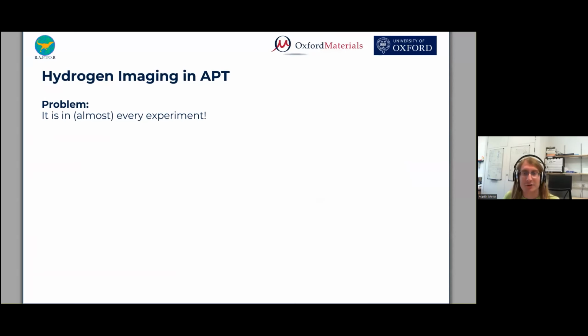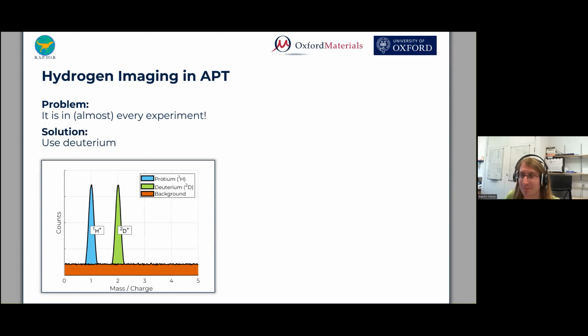We briefly return to the introduction. I said imaging of hydrogen is difficult because we never can be sure if the hydrogen is coming out of the sample or if it's just a contaminant signal. The common workaround used in the literature is this: we use a deuterated sample, and then we fiddle around with the parameters until we get a spectrum that looks like this. So separate peaks for contaminant hydrogen plus and deuterium plus that's coming from the sample.